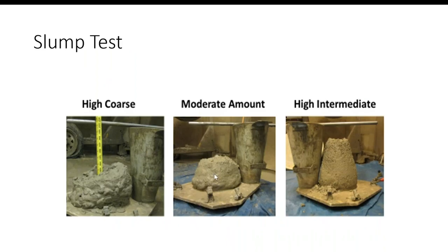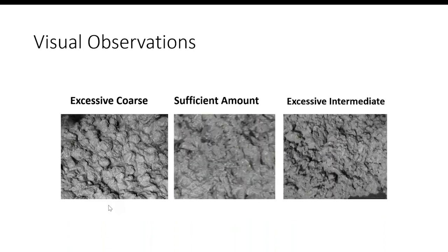If I was right here in the middle, everything was great. If I had too much of that intermediate, not good. If I had too high of the coarse, it's actually segregating. See the rock coming out of it? That's not good.